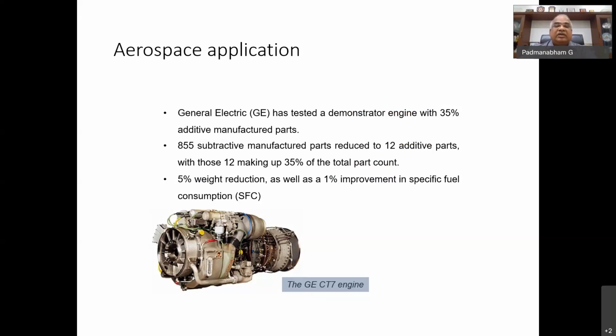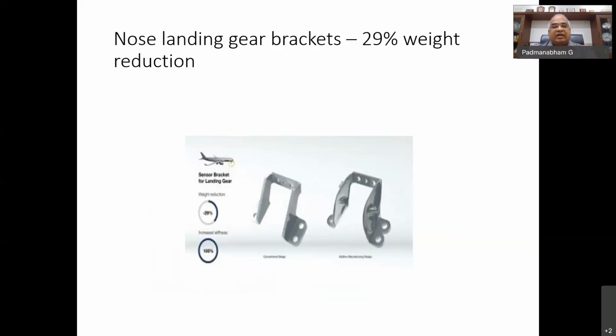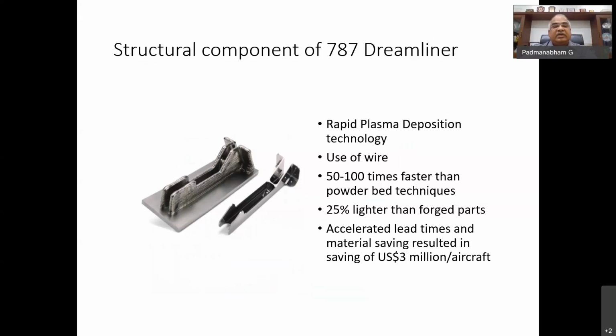It helps a lot in productivity, and it's not only productivity, but it showed that 5% weight reduction is possible, and that leads to reduced fuel consumption. Again, another example of weight reduction, what you make conventionally and what you can make using additive manufacturing. Another structural component uses plasma deposition technology. Even though it is a coarse deposition technology using wire as the feedstock and a plasma torch as the heat source, productivity has also been improved substantially. You build a near net shape component 50 to 100 times faster than the powder bed techniques, but 25% lighter than a forged part. They were able to develop this component very fast, with a saving of about $3 million an aircraft.